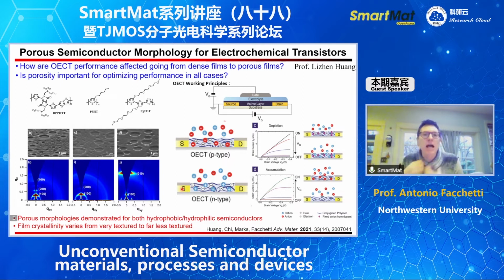So the question we ask ourselves is, if we make porous films of different semiconductors versus dense films, is this important for an organic electrochemical transistor? Is it always important or not? This is basically the question we ask ourselves. To address this, we use 3 different polymers, and for all of these polymers we have been able to create conditions to achieve films which have porosity, and the films are also semi-crystalline. These 2 films are much more textured compared to this third film.